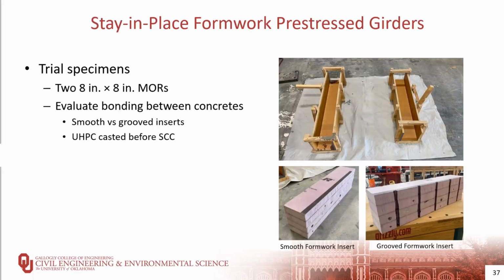So the stay-in-place formwork girders were still not yet cast, but before we finalized the design, we actually did trial specimens. Those trial specimens were done to evaluate the bonding between the UHPC and the SCC concretes. Two interfaces were chosen for these trial specimens, the smooth and the grooved inserts.